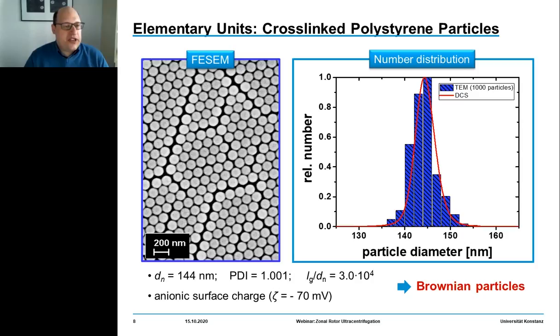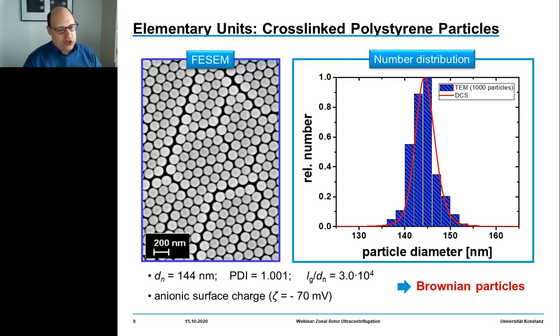The colloidal molecules we would like to discuss today are assemblies of uniform polystyrene particles, which are highly uniform and can be prepared at large scales. So here, sorting is not yet an issue. These particles have dimensions on the order of 100 nanometers, which means these particles and small clusters exhibit Brownian motion that prevails over sedimentation.